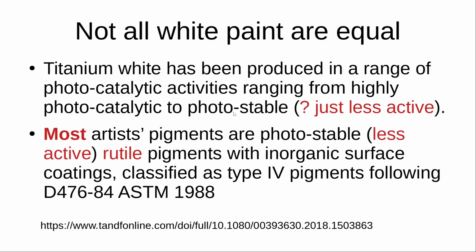So not all white paints are equal. They might have the same chemical formula, but you do get different types of titania, and it depends on their crystal structure. According to this article, they are talking about some titania being photocatalytically active and some being photostable. Now, in my mind, I don't agree with this word photostable. I will give you some proof in a future slide. I'd rather say it's just less active. So all titania is catalytically active. It's just a question of how much.